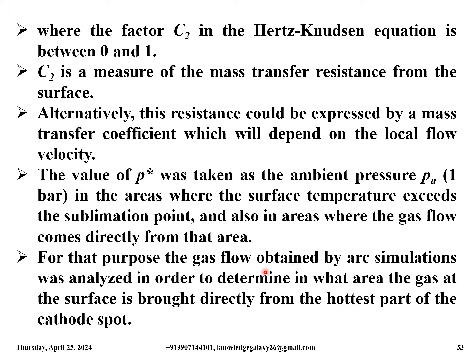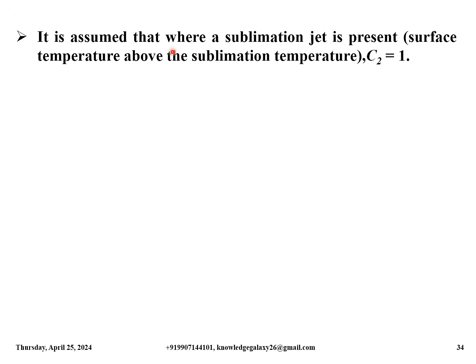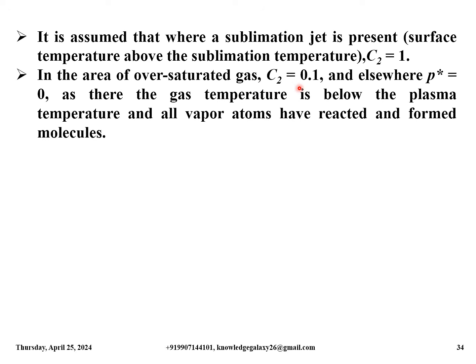For that purpose, the gas flow obtained by arc simulations was analyzed in order to determine in what area the gas at the surface is brought directly from the hottest part of the cathode spot. It is assumed that where a sublimation jet is present, surface temperature above the sublimation temperature, C2 is equal to 1. In the area of oversaturated gas, C2 is equal to 0.1, and elsewhere P star is equal to 0, as there the gas temperature is below the plasma temperature and all vapor atoms have reacted and formed molecules.